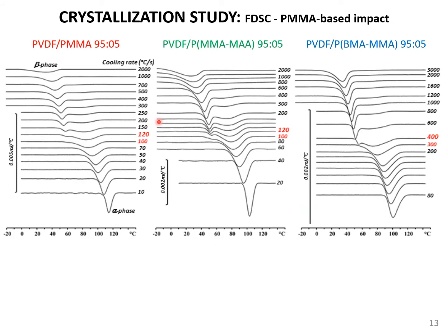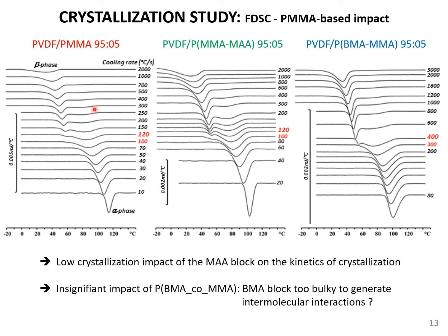This is the result we obtain for a blend containing 5% of this derivative PMMA. You can see the PVDF containing PMMA with methacrylic acid, and the PMMA containing butyl methacrylate. For the two first examples, you see no difference in terms of crystallization, indicating that we don't have any negative or positive effect by adding methacrylic acid.